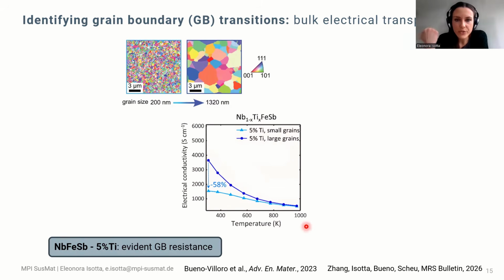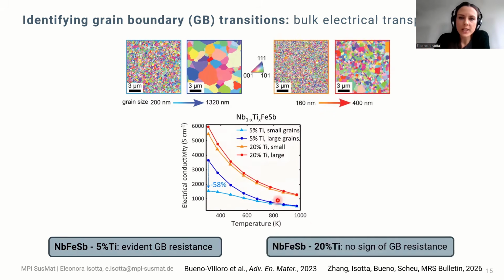What was very interesting instead was that when 20% titanium was introduced as a dopant, no sign of grain boundary resistance was noticed, because the behavior of the electrical conductivity was basically the same as the single crystal behavior — no grain boundary activated transport, regardless of grain size. So even by changing the grain size in the sample, the behavior was the same and not associated with grain boundary resistance.